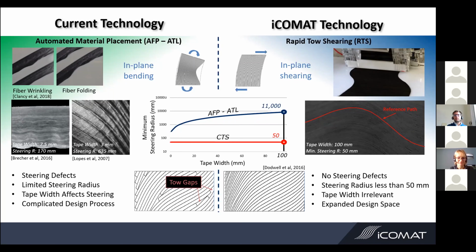However, with Rapid Tow Shearing, iCOMAT's technology, because it's shearing and not bending the tapes, we are able to steer around really, really tight radii, as low as 50 millimeters. So that's an order of magnitude improvement compared to the state of the art. Another point is, again, because we're shearing, there is no limitation to the width of tape that can be used. So our current machine is set up to work with tapes up to 100 millimeters wide, which is pretty wide for this kind of thing.